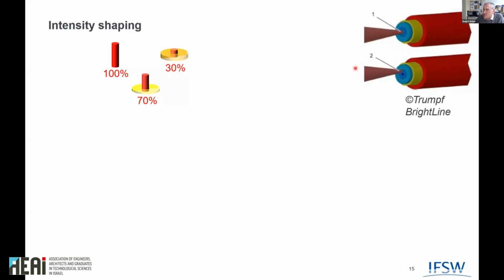And now to another system of beam shaping. This was originally presented by Trumpf, called bright line weld. This is a two-core fiber. We have an inner core and an outer core, and the power can be distributed between the two cores, which is schematically shown here. For example, you can make everything in the inner core. You have something which is a little bit around, or you have most of it in the outer core. Even larger doesn't make sense.